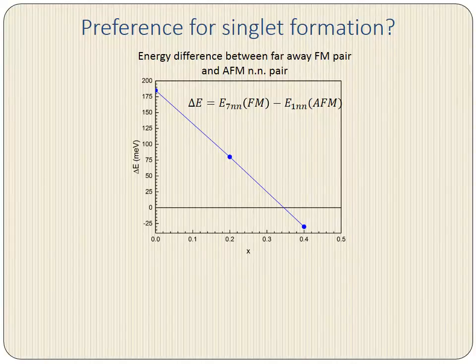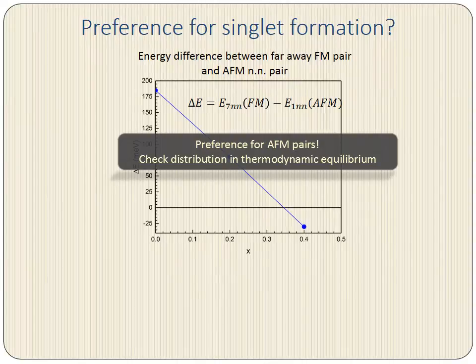We return again to our total energy calculations. We take a look at the energy difference between a faraway ferromagnetic pair and an antiferromagnetic nearest neighbor pair. When we look at the following plot, we see that for most hole doping levels, there is an energetic preference for the formation of singlets. This indicates that there might be a statistical weight that prefers singlet formation. Furthermore, in the experiment, the thermal preparation protocol was to anneal the sample to 1000 Kelvin, then slow cool it down to room temperature. This provides plenty of thermal energy to promote singlet formation, so we should check the singlet formation in a sort of thermodynamic equilibrium.